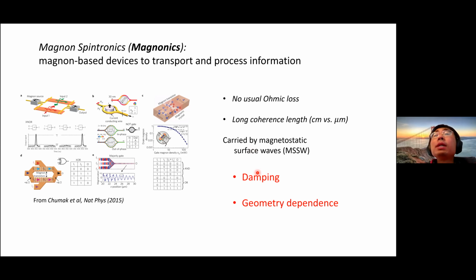So the first major problem is about damping. This damping results in a finite lifetime of these magnons. We know that magnons are collective excitations inside a quantum magnetic material when the system has certain order, and these magnon excitations typically have a finite lifetime. This finite lifetime leads to a damping of, for example, surface waves. So this is one important issue that needs to be addressed in the magnon spintronics application.